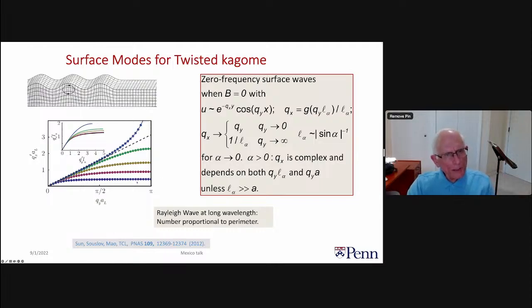And all of these lines asymptote to this straight dotted line, which is exactly what you can find if you look at Landau and Lifshitz mechanics. It calculates the surface Rayleigh wave, and it has exactly this form for its energy if you have a system with 0 bulk modulus. And we told you that these are for the twisted lattice, and that we have exactly the same long wavelength sound or surface velocity as calculated directly from the elastic theory.